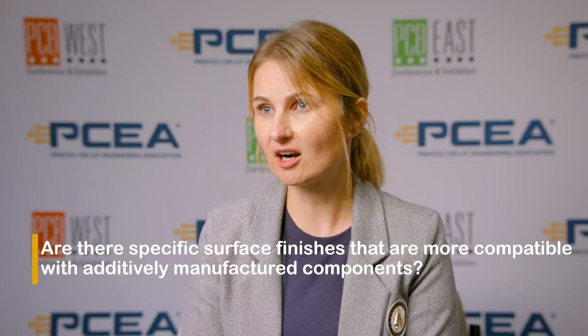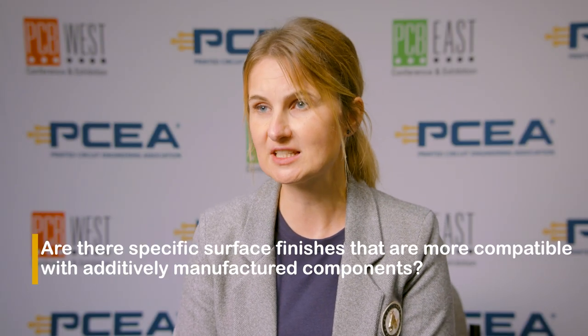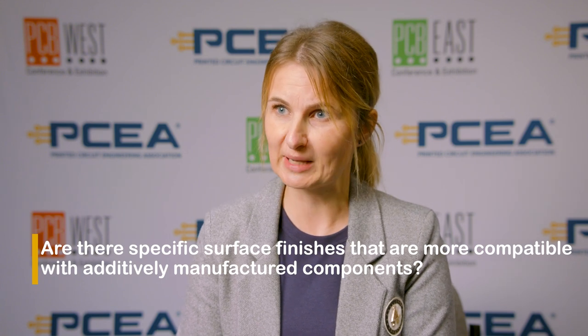And then one of my favorite applications is going to be 3D printed polymer PCBs, which are going to be plated, normally electroplated. There are some surface finishes that are compatible with the additively manufactured surfaces. One of them is already mentioned, the plating on plastic. So for the 3D printed polymer based PCBs, we might also be having a look at some other techniques related to more advanced coatings, as already mentioned, carbon or graphene ones. We might also be looking at hybrid surface finishes, when again we are going to have the combination of different individual surface finishes in order to obtain multifunctionality.